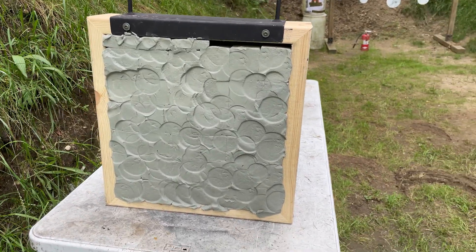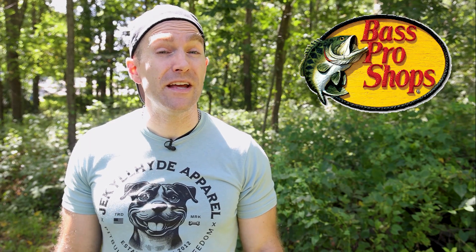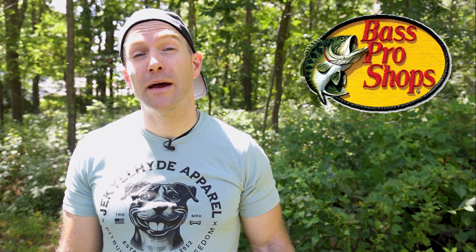If this is the first time you're viewing my YouTube channel, we do all of our body armor demos completely different than everyone else on YouTube — worst-case scenario. Since this is rifle armor, we shoot at 45 feet at zero degrees because that is maximum worst-case scenario for that body armor. Any oblique angles only add to the amount of material that bullet has to penetrate through. We also use a giant clay briefcase filled with Roma Plastalina number one clay from Chavant as our compressible media. It prevents the body armor panel from flying about and ensures maximum energy transfer. It's the same clay the NIJ uses. I have an affiliate link in my description below if you're looking to make a purchase from Bass Pro Shops or Cabela's.